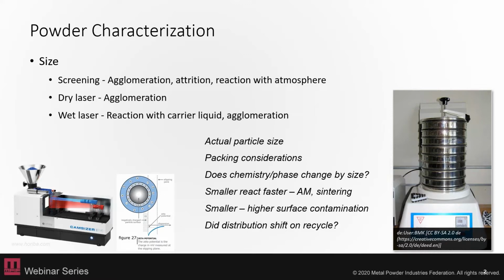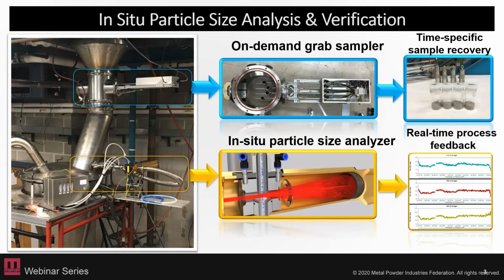One area that we looked at too is being able to look at your particle size distribution in situ. So you could consider being able to do on-demand grab sampling during your powder process. I know many AM machines will have a build volume or a plan that you can use that will capture powders within a melted volume. And so you can take that sample and keep it on hand as an archive for a representative distribution of the powders that you were using for a particular build.